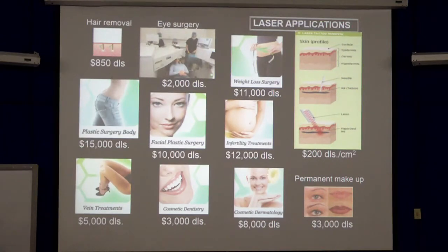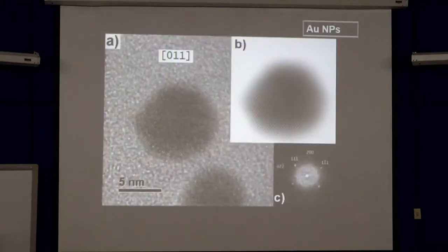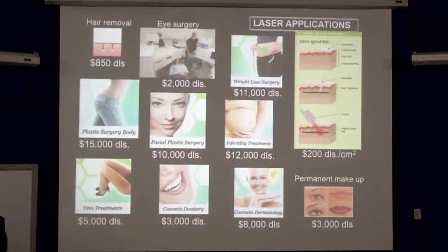And with nanoparticles, you can modulate the transmittance of the beam in ultra-fast time. This is very important because you can eventually damage different regions that are not located in the incidence of the spot, but the propagation of the heat can damage collateral regions of the incidence.